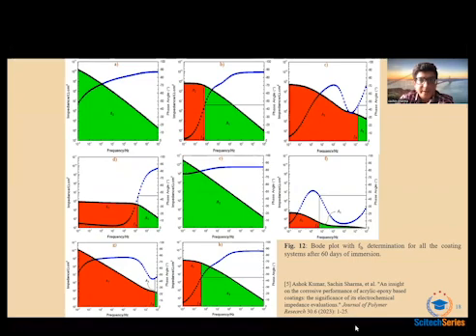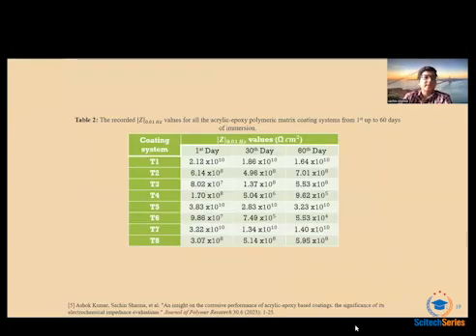However, figure 12 illustrates the breakpoint frequencies at the end of the 60th day of immersion, and we can still see over here that figure A and figure E, which is the T1 and T5 samples, still maintained a complete capacitive region. However, for G, it started to show that the electrolyte ions have quickly penetrated, okay, through the layers of the coating. However, it still maintained a strong barrier against the corrosion attack. So this table 2 illustrates the recorded Z impedance value, okay, at 0.01 hertz for all the polymer matrix that were fabricated, and the coatings were exposed up to 60 days of immersion.